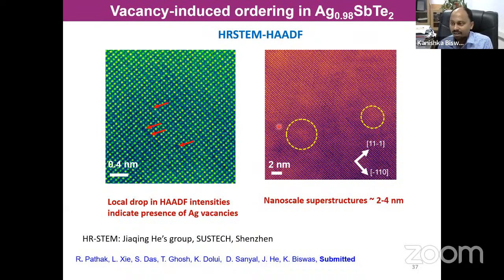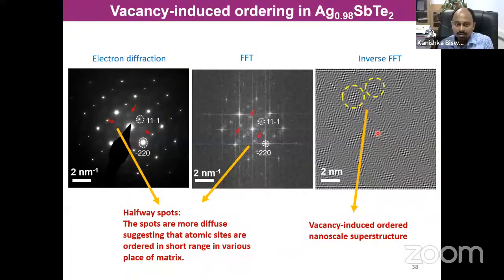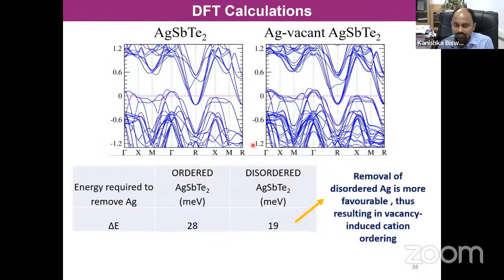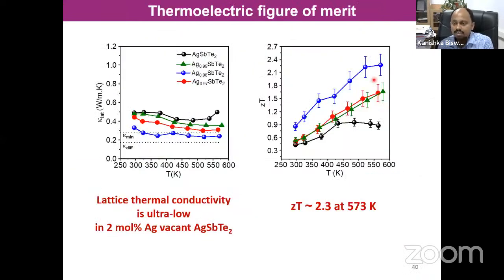Okay, and near the silver vacancy position, we see this atomic ordering, which is again 2 to 4 nanometer in size. We have done extensive TEM to understand this vacancy-driven atomic ordering, and this also gives rise to a ZT of 2.3. We have submitted this paper now for publication, and we have done a much more detailed study in this.